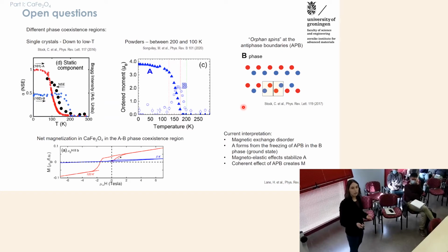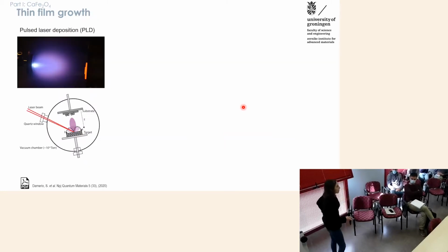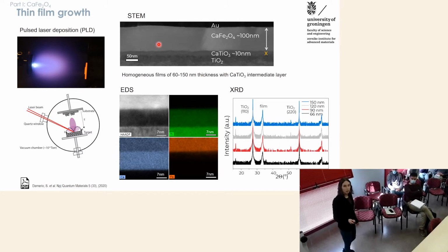And this difference between single crystal and powder sample made us think that it was really interesting to study also films of this material, because strain has been considered as a possible cause of the difference of magnetoelastic coupling in the single crystal and the powders. So we decided to grow films of this material and study them from their magnetic point of view, which I've never done before. So the first part of the work was about growing these films, and we chose a PLD method. In brief, we made our own targets, and with the laser, we ablate the target and generate a plasma plume that deposits the material on a heated crystalline substrate, and we anneal by cooling down from the high temperature. And we grew our films on titanium oxide substrates.